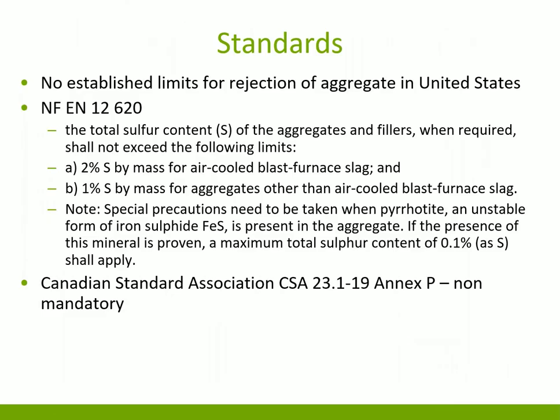The Canadian Standard Association has been doing a lot of research, and they have developed a testing regime for evaluation of the total amount of sulfur in your aggregate and whether it has a potential for damage. That is actually an appendix to their standard, which means it is not mandatory at the time because they are doing additional testing to come up with the correct values. But they do have a nice program that I am going to go over real quickly, because really it is the best avenue for us to go down at this time.